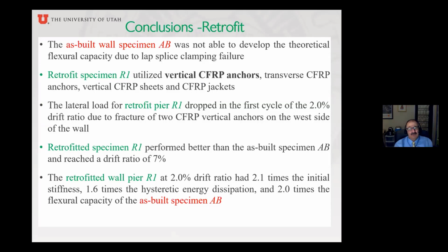It dropped after the first cycle at 2% drift because two of the vertical anchors fractured on the west side of the wall. On the east side, though, where the anchors didn't fracture, it behaved very well. Actually, this retrofit performed better than the as-built and reached a drift of about 7%. So the retrofit at the 2% ratio, where we see the first drop, had 2 times the initial stiffness, 1.6 times the energy dissipation, and 2 times the flexural capacity of the as-built.